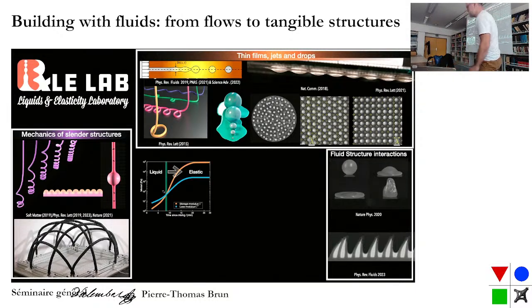And the way I want to introduce this idea is through a little bit of rheology. So this is the rheology of an elastomer that's cross-linking. You don't see the line very well, but the blue one basically is a loss modulus, so it tells you how liquid something is. And the orange is the storage modulus, so it tells you how elastic something is. So you see that at the beginning, blue is above orange, and it's a log scale, so it's more viscous than elastic. And at the end, it's more elastic than viscous, right?